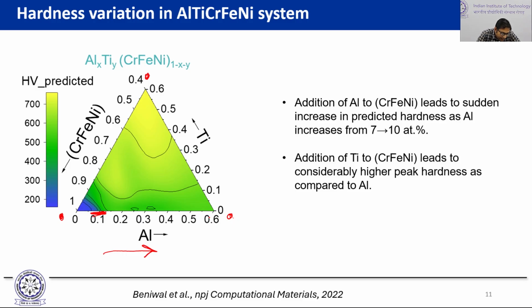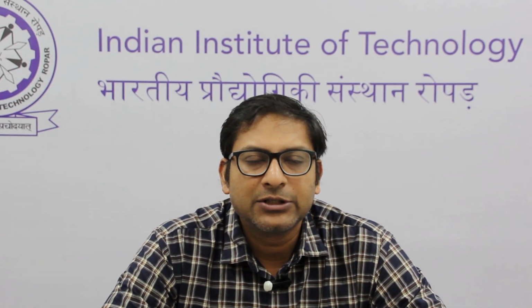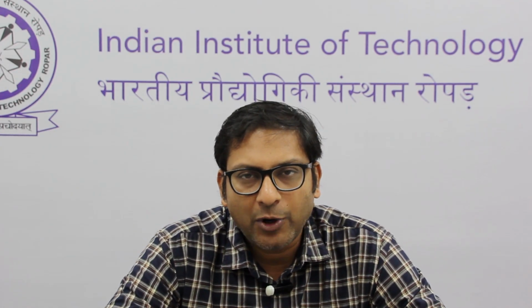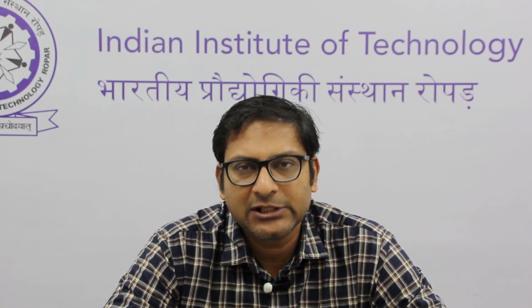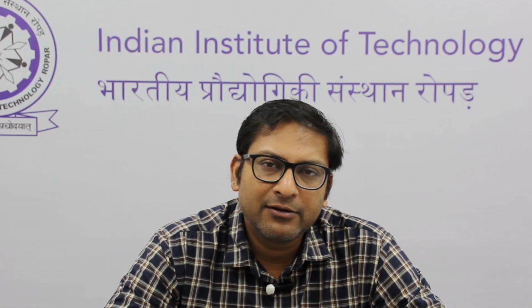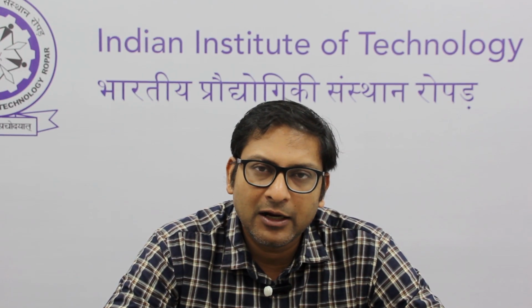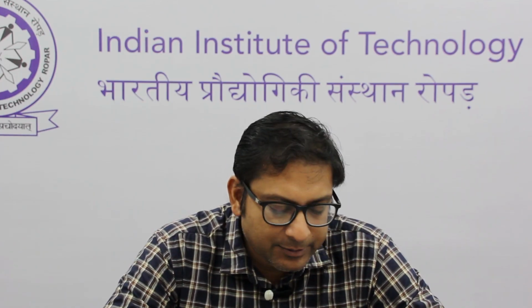So one of the things you can figure out is the reason for this jump quite likely is going to be a change in the crystal structure, possibly from a FCC type of phase to a BCC type of phase, because that results in going from a high number of slip systems to a low number of slip systems.